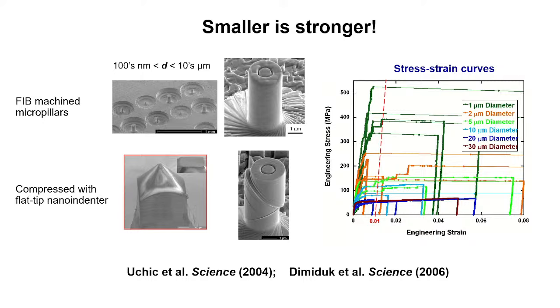pillars that are 1 micron in size, and you have a well-annealed single crystal, 1 micron, right? The pillar should on average contain no dislocations. So a 1 micron pillar should contain no dislocations. So why is it that you're not getting the theoretical strength? The theoretical strength should be on the order of gigapascals, not megapascals, right?